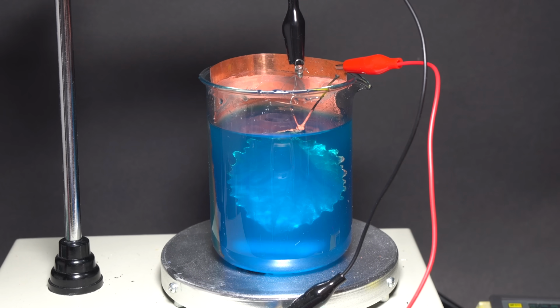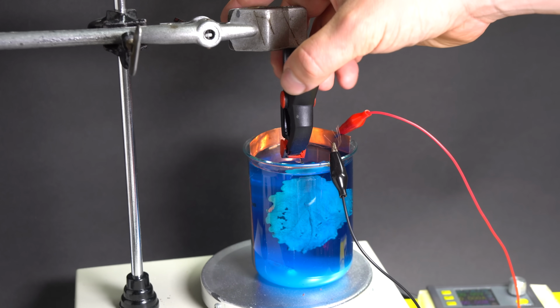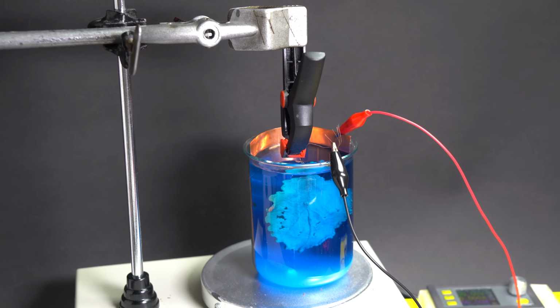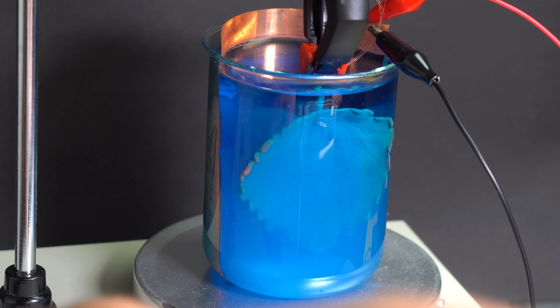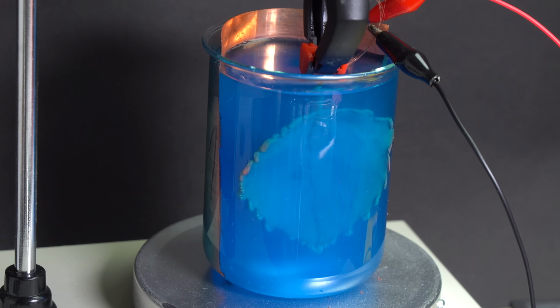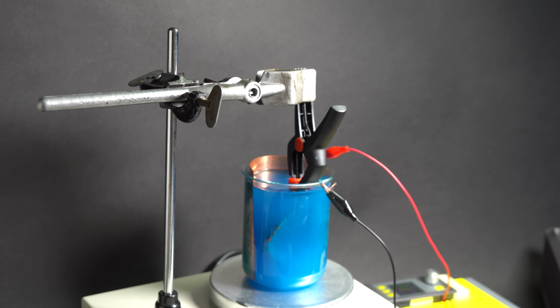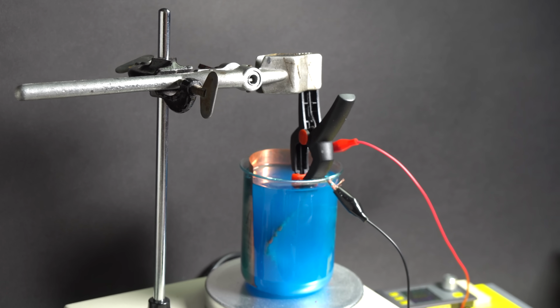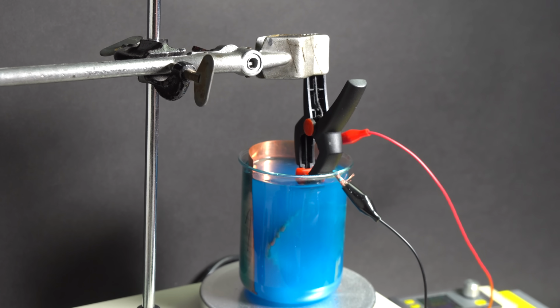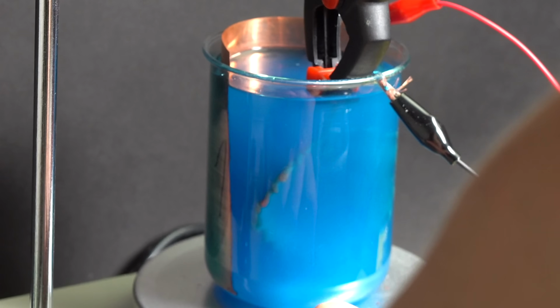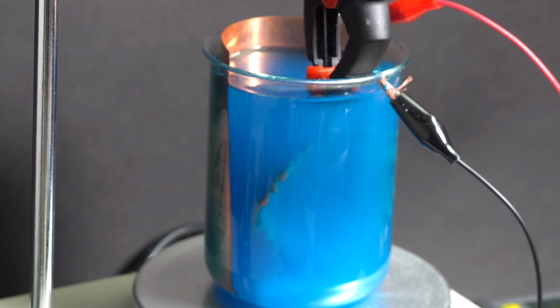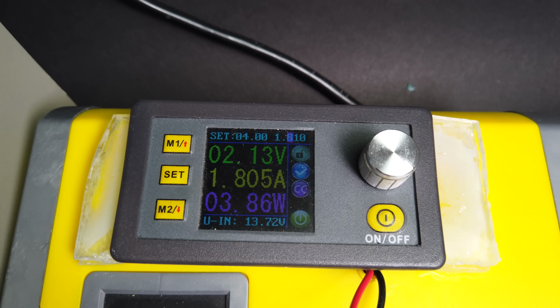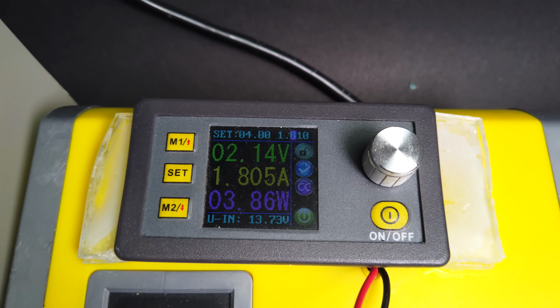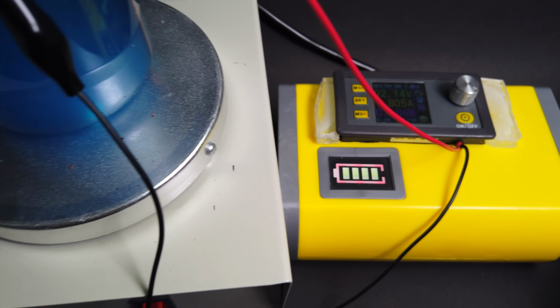In practice, without stirring the solution, my leaf was taking too long to cover in shiny layer of copper. That is why I decided to stir it and increase current. Because of thiourea in the solution, there formed sediment, most probably consisting of 1-valent copper compounds, which is why current had to be increased by more than 3 times to ensure an even spread.